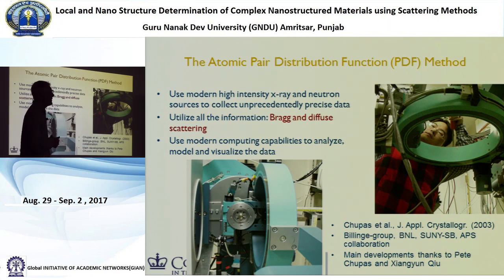So from some strongly scattering material like nickel, it went from a 12-hour measurement to a one-second measurement. So we got a 4-order of magnitude increase in throughput. And this basically revolutionized this method, because now, if you had access to one of those synchrotrons, you could do these experiments very rapidly. And so it started to become interesting to chemists and material scientists who wanted to characterize their material, not do some heroic measurement that took a very long time.